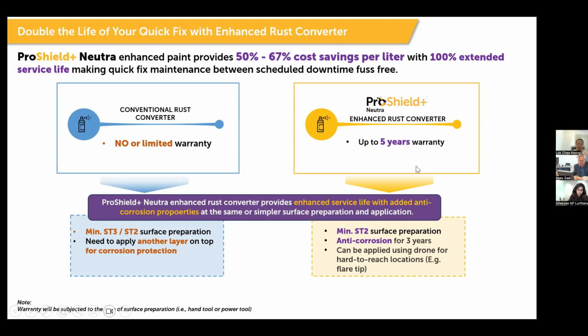With our enhanced rust converter that we have developed with Kossan paint, all you need is at minimum wire brushing. And because it has very good adhesion properties, at the same time it creates those barriers, today we're able to see extended service life of up to 3 years. And it can also be applied using drones for hard to reach locations.